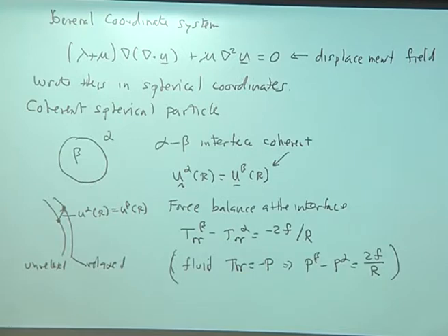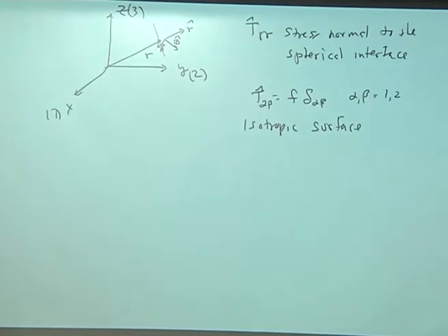So it's basically the same thing, except expressed in terms of stresses. That's why the change in the sign here, the TRR is minus the pressure. That's kind of a definition that people use. Okay, and so these are the two conditions that allow us to patch the equations up at the interfaces. This is the classic sharp interface model. And now we need far field conditions on the...